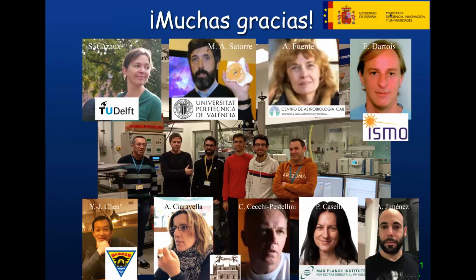But you don't have this kind of experiment planned? We haven't done them ourselves, to mix the dust with the ice. We haven't worked on that. We could do it in principle, but we haven't done it. One of the reasons why we didn't do it is because if you are working with the best vacuum conditions and you put dust in there, you pollute the chamber. So for this, you need a poorer vacuum so that you can clean the chamber more easily. But it can be done.